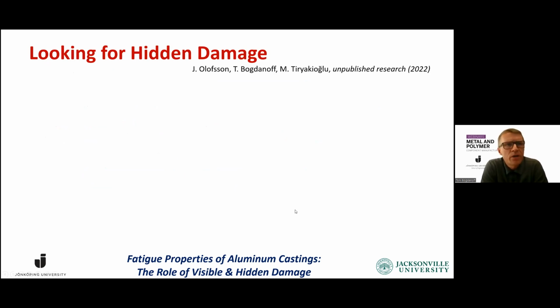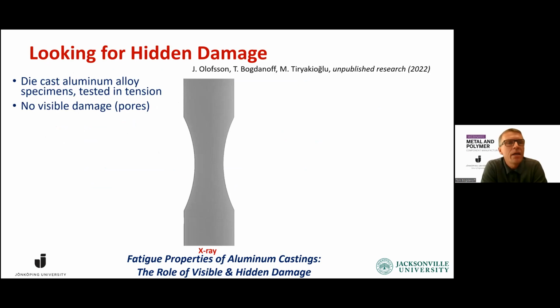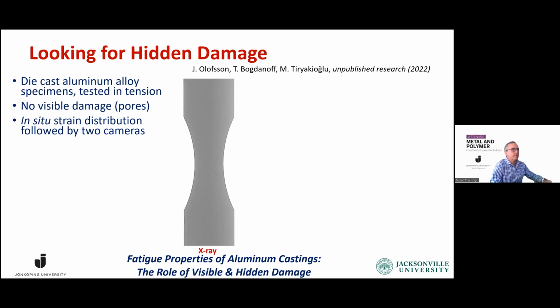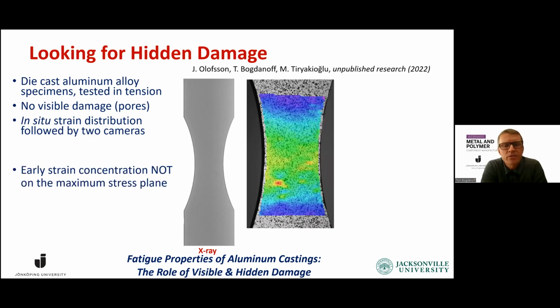We are doing a test on die casting aluminium alloys that has been casted. And then we did X-ray on the sample where we didn't see any visible damage at all, in this case porosity. And then we used digital image correlation using MatchID to actually follow in situ strain distribution with 2 cameras in this case. And what we see during the tensile test is that we have regions where we see a clear high strain concentration. That will actually be the final fracture place as well.